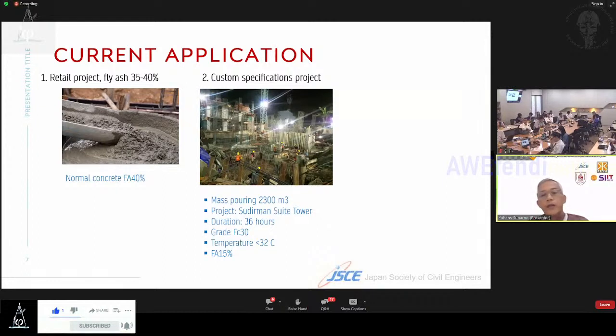And the request for the temperature is a maximum of 32 degrees Celsius. So in the concrete, we use fly ash of about 15%. And to minimize the temperature, we use ice. So the temperature is still under control, less than 32 degrees Celsius.